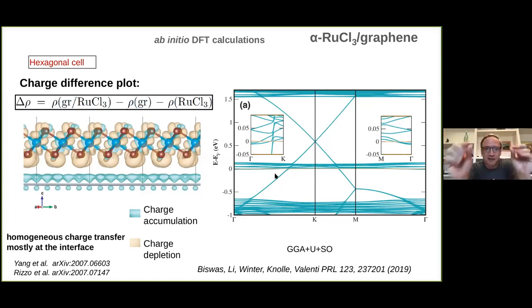No, I'm not even asking about that. Just the radius of it. There's the point where you have the cone coming out, and just literally, what's the Fermi wave vector, measured away from K? It looks like a circle. Just that carrier density, pi kF squared over 2 pi squared. I don't have it in the form you would like, but what I can give you is the number of electrons per unit. So the number of electrons is about minus 0.064 electrons per ruthenium chloride unit. It's small.